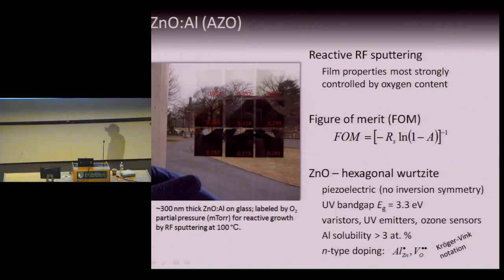This optimality is measured by a figure of merit. Everything needs a figure of merit. This figure of merit combines the resistance and the optical absorption in just such a way to cancel out the thickness dependence. So you can grow your films, measure the resistance, measure the absorption, and then put the film you just grew on a plot and see whether it's good or bad.